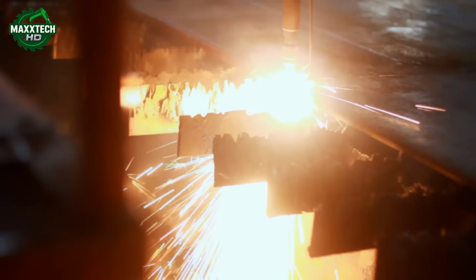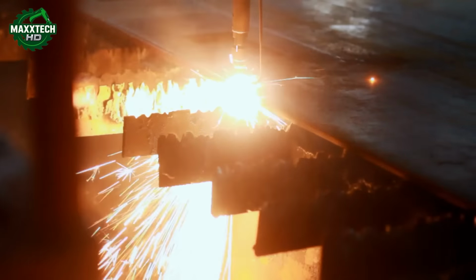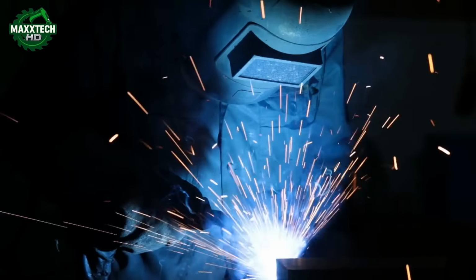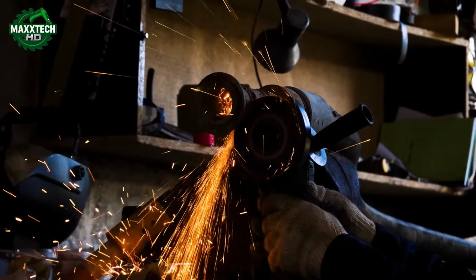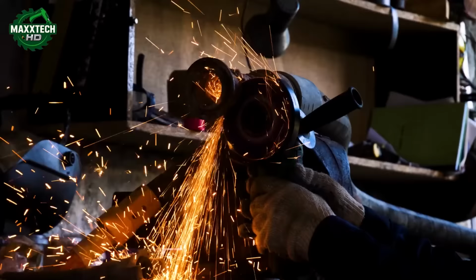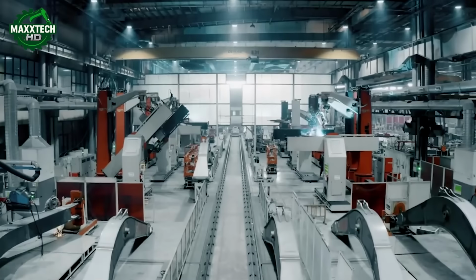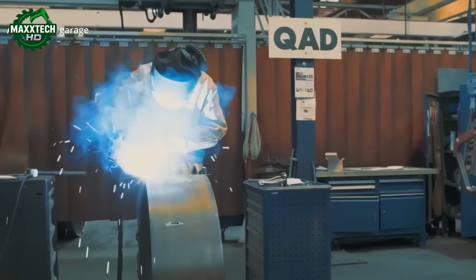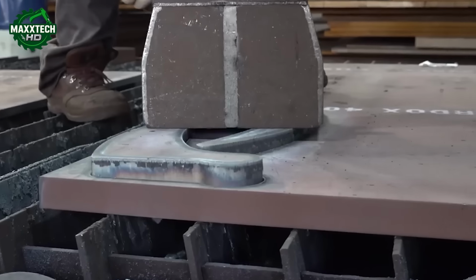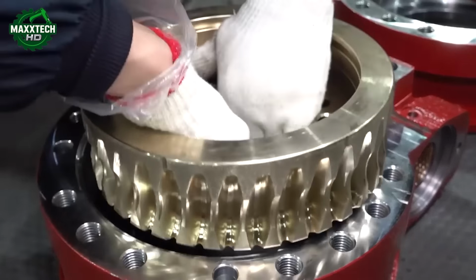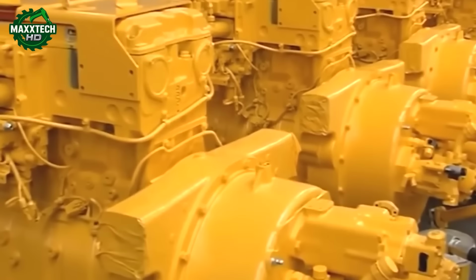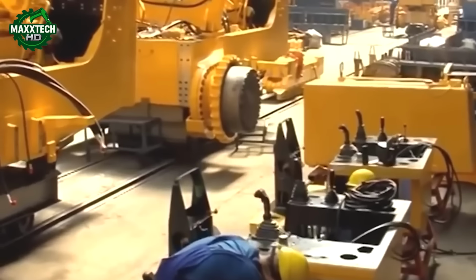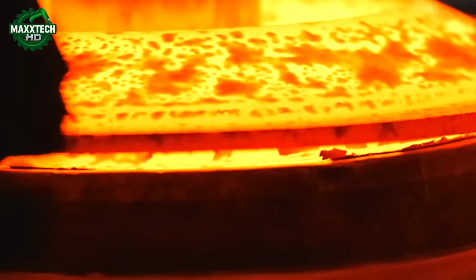At first, it looks rough, studded with jagged nubs like a porcupine. Crews cut, chip, and grind the metal smooth, preparing it for the final critical step: heat treating. Heat treating transforms the hardened steel into something both strong and flexible, allowing the frame to bend over rough roads without cracking. For several hours, the metal is heated above 1,652 degrees Fahrenheit, then slowly cooled, letting the molecules rearrange into bonds that are tough, yet resilient.